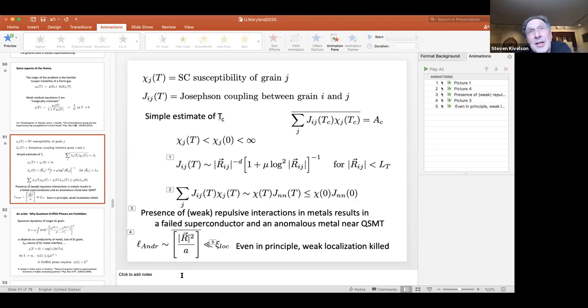As you start tuning away from the transition and the superconducting fluctuations become less and less, then this should be a diffusive metal. And then ultimately the question is, why, once it's there, doesn't it localize? And sometimes it does, as you saw in Charlie Marcus's data, when we get far enough from the transition, we actually have another transition to an insulating state. That should be a true quantum phase transition. But between the anomalous metal and a Drude metal, it's a crossover, as far as I know. So the mysteries are to understand why it doesn't become a superconductor, what's the nature of the transition, how do you account for the temperature dependence of transport, things like that?